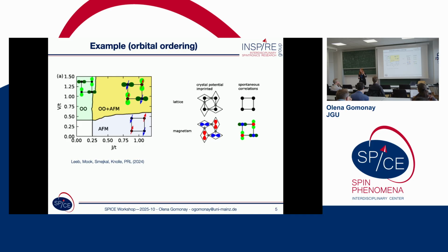Before I go further to manganese 5 silicon 3, I would like first to thank the first speaker of this session for showing this type of phase diagram. What we suggest is something similar to what is shown there. In phenomenology, the altermagnetic order parameter can be related to the symmetry of the orbitals or to the symmetry of the crystal environment. It does not matter from the point of view of this mean field theory, but in this phase diagram you see that you can go from the antiferromagnetic to the altermagnetic phase. You can go first to the altermagnetic paraphase and then to the altermagnetic phase, and so on. So this type of transition in principle can exist.